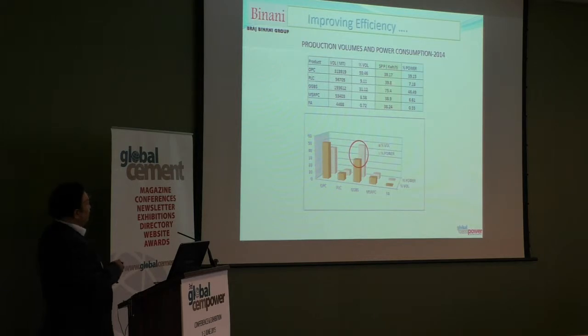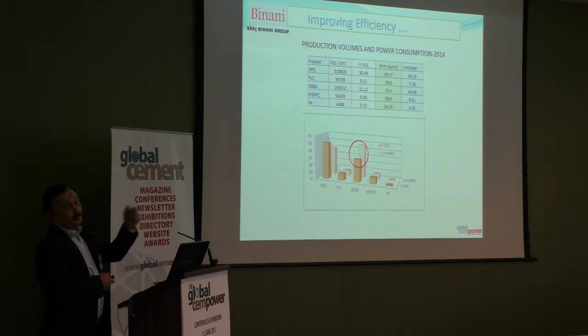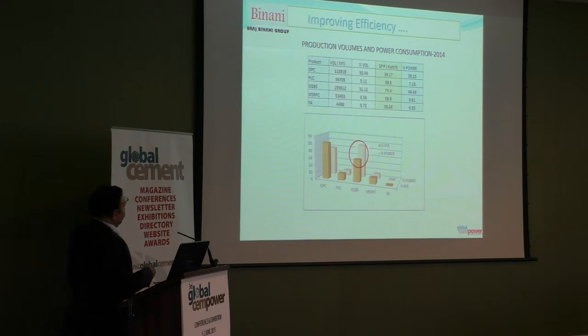But in terms of plant performance, this is what we have done in the last year. Now, what is important here is that this is a normal scenario when we look at clinker-based product. Normally, you consume under 40 units. This is okay. But the real problem is slag. So we consume 75.4 units. What is interesting is that in terms of contribution towards total power, this is totally reversed. So slag with a lesser volume is contributing a larger share of total power. Now this is our major pain area. So this is the volume produced. We produce only 31%, but in terms of contribution towards total power, it is almost about 47%.